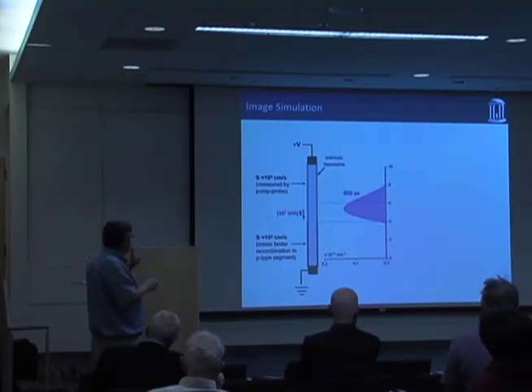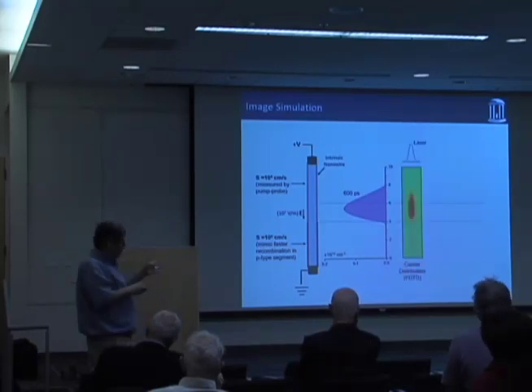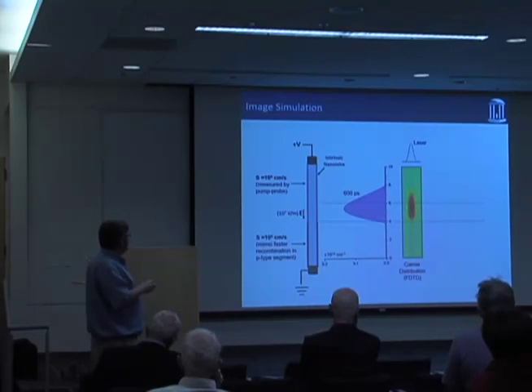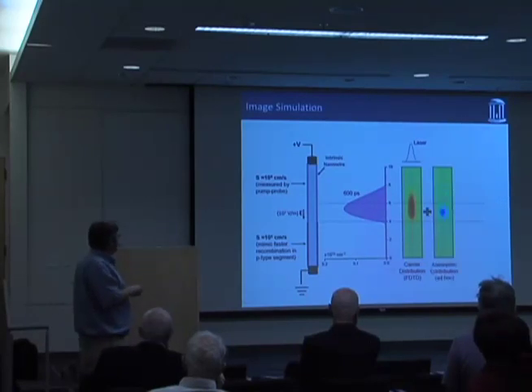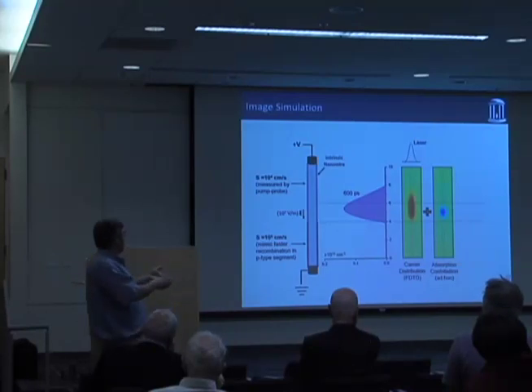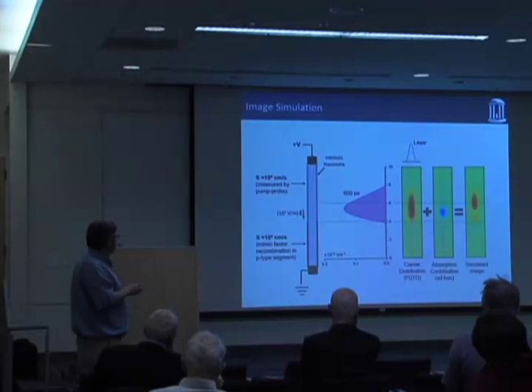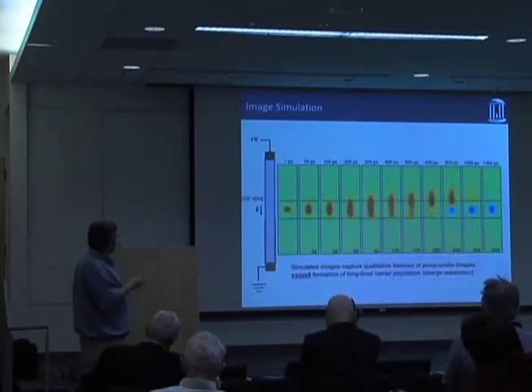But anyway, so we'd use that, and we could just convolve that with the Gaussian, and we could create an image that looks like sort of what the free carrier contribution to the images in our transient absorption experiment would be. We also have in the experiment this sort of absorptive component, which we can't get rid of. So we're going to just sort of add that in as kind of an ad hoc way. And we actually got the size and sort of the amplitude from the frames that we collected at really long delays in the transient absorption experiment. And if you add those two things together, you get something that starts to look very similar to what we have in our experiments. And so what we did is we did this for a whole bunch of different times, and this is what you get.